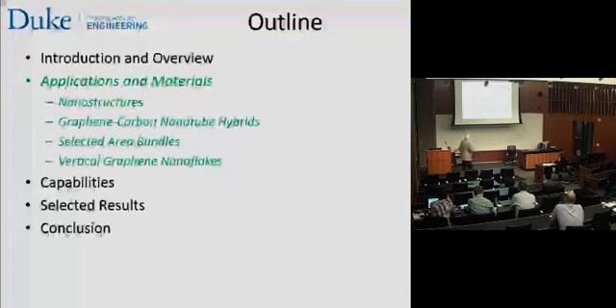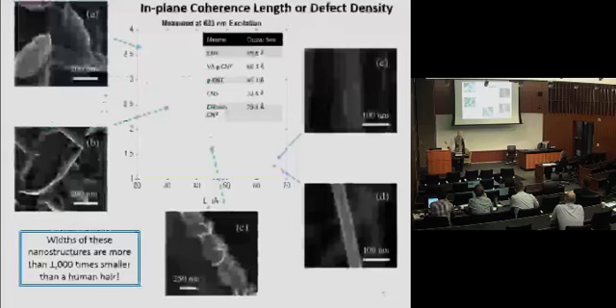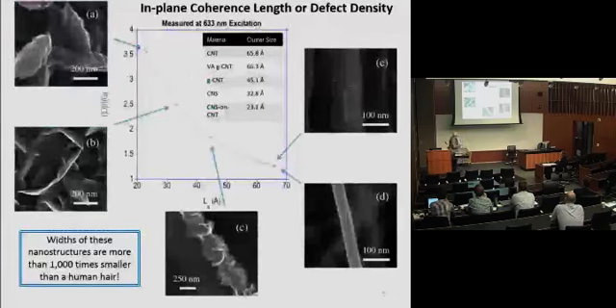We want to talk a little bit about the nanostructures that we grow, the nanotube hybrids that I mentioned, the graphene carbon nanotube, and then selected area bundles and vertically grown graphene nanoflakes. The reason I bring this up is because there's a lot of pretty pictures here. So I can just zip through this and show you the structures that we're looking at when we talk about our nanomaterials. So shown here is, you don't need to know a lot about this graph, but you can think about this as the distance between defects. And you can imagine that some materials we'd like to have very few defects, but you can also imagine, especially with electrodes, we'd actually like them to have a lot of defects. The defects are actually the advantage of these materials.